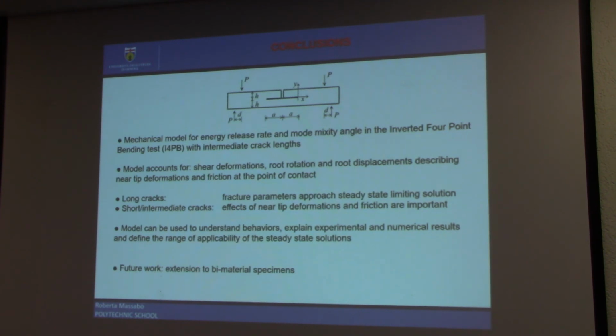So we formulated a mathematical model for the inverted 4-point bending test, and the idea is to account for shear deformation, for root rotation and root displacement, which describe the near-tip deformation ahead of the crack tip. We account for friction at the contact point. We noticed that for long cracks, the fracture parameter indeed approaches the steady-state limiting solution, but for shorter, intermediate cracks, the effects of near-tip deformation and friction are very important. The model can be used to understand the behaviors, to explain experimental and numerical results, and to define the range of applicability of the steady-state solution.